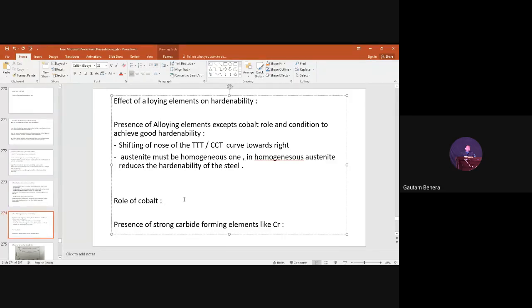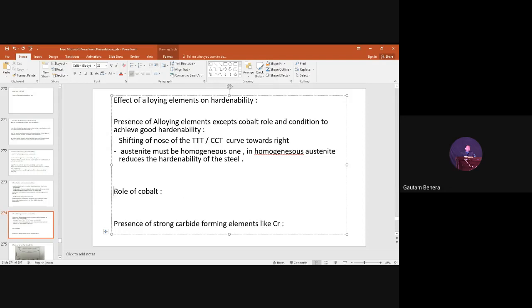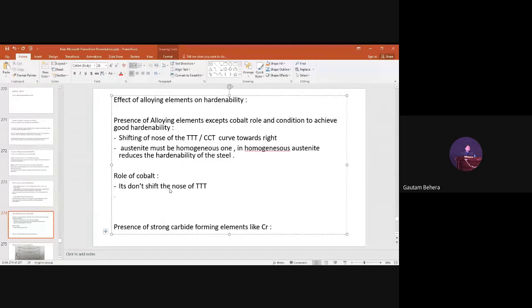Cobalt, I already told you, is the exception which does not shift the nose of the TTT curve, the CCT curve, towards the right. So if cobalt is present, what can I write? First thing, it does not shift the nose of the TTT curve. And also, it promotes the nucleation and growth of pearlite.